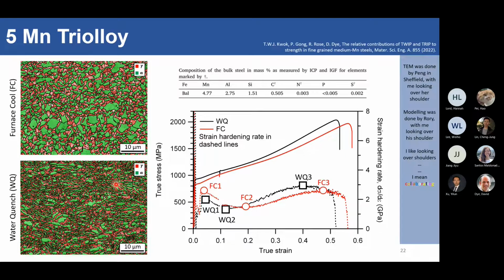And this is from the same composition. So we had one composition, but processed differently to give you two different types of microstructures with roughly about the same phase fraction. So they're both about 50-50 ferrite and austenite. And when we did a tensile test, lo and behold, they actually deform in almost exactly the same way. They have that very nice shape, up, down, up curve again. So your water quench sample is slightly stronger. That's because your lamellar thickness is a lot smaller, so you get a bit more grain size hardening from that.